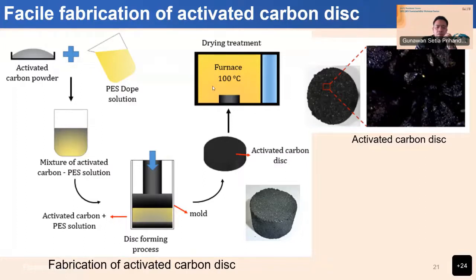After that we put the disc into the furnace at 100 centigrade for 1 hour. Actually, we can also just leave it outdoors. You don't have to put it in the furnace, but to make sure it is stable for the purpose, we put it in the furnace to dry the membrane, to make sure there's no NMP inside the disc. Once we have this, we put it into the water to check the bond between the activated carbon powder and the membrane. Then we can start the characterization process of the disc.